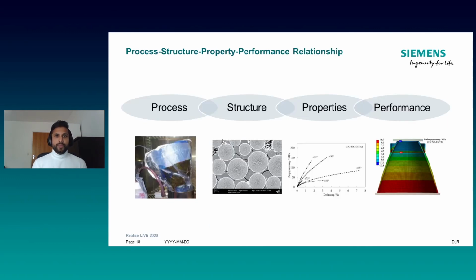So in this manner, we come back to our process, structure, property, performance relationship, where we said that we want to establish a relationship between process, where we have manufacturing parameters, for example, fiber, matrix, and the pyrolysis temperature, and so on, and when we end up with a structure. So this is the area where we modeled everything right now. We started with some process parameters, and we ended up with a structure. And in the next step, if we take this structure and apply a certain thermomechanical load to this particular structure, we end up with a performance.